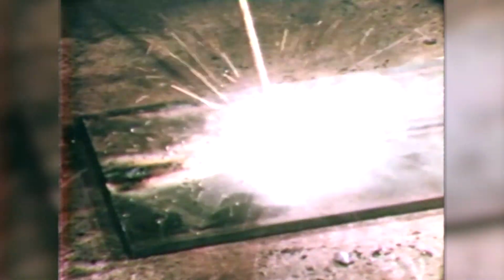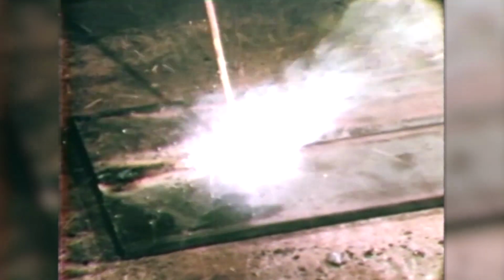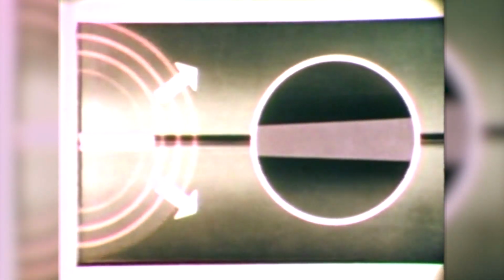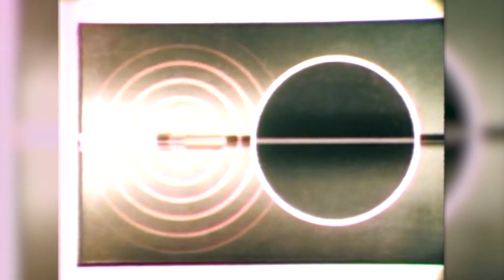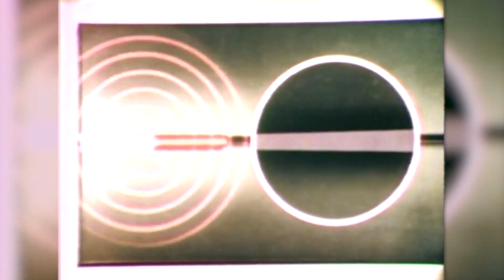To illustrate this method, very short welds are used here, but in actual practice, each bead is laid with 1 stick of electrode to allow time for the heat from each weld to distribute evenly throughout the plates before beginning the next bead. When we use backstepping, notice how heat from the first weld causes expansion which temporarily spreads the plates. But as the heat moves out across the plates, the expansion in these outer areas, acting against the bead which is cooled, forces the plates together. Each weld becomes a rigid section by the time the next weld is started, so that the spreading action becomes less and less with each succeeding bead, until the weld job is completed without further spreading or distortion.